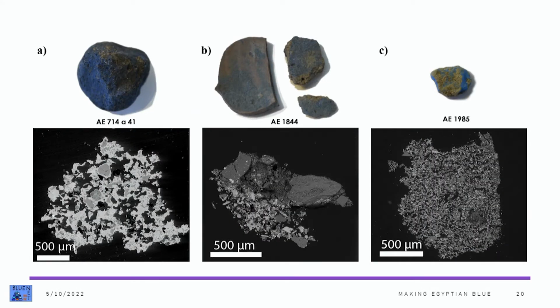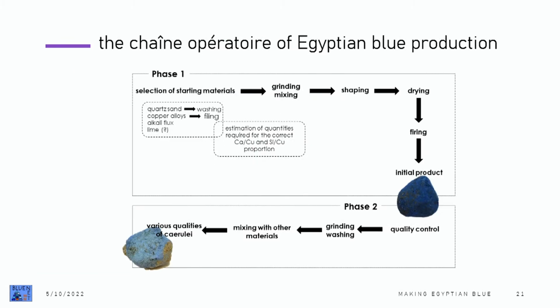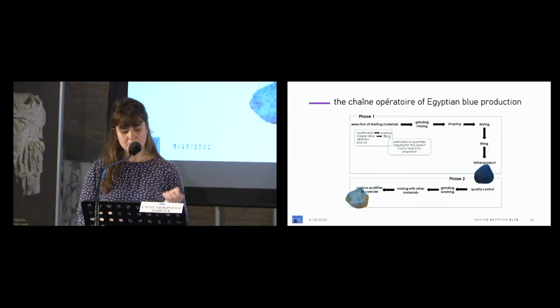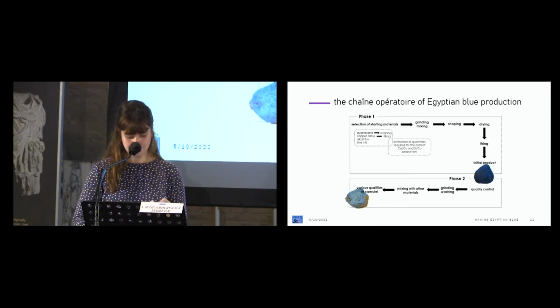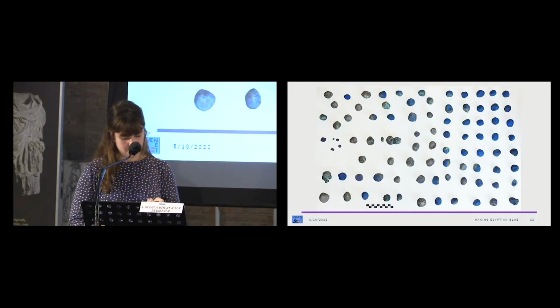Beyond the production of the initially produced Egyptian blue pellets, the Kos material demonstrates that the materialization of different tonalities of blue took place at the workshop through the further processing of the initially produced pellets. Microanalytical investigation of the finds suggests that 2 variations of the manufacturing process were carried out at the same site to produce different tones of blue. The Kos workshop therefore demonstrates the complexity of Egyptian blue production, which might result into pellets of different composition, depending on the starting materials used.